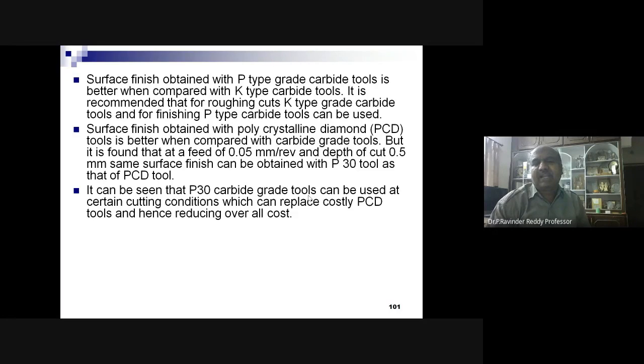Surface finish obtained with polycrystalline diamond tools is better when compared with carbide grade tools, but it is found that at a feed of 0.05 mm per revolution and a depth of cut of 0.5 mm, the same surface finish can be obtained with the P30 tool as with the PCD tool. It can be seen that P30 carbide grade tools can be used at certain cutting conditions, which can replace costly PCD tools and hence reduce overall cost.